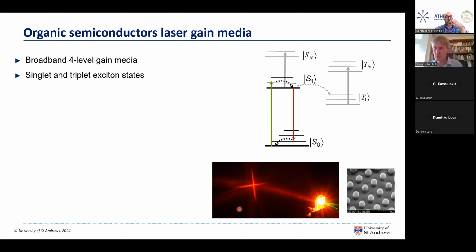So what about laser materials? Organic semiconductors are also quite interesting as laser gain media because their energy level systems are amenable to making a broadband 4-level gain medium, where we go between two electronic states in the molecule and a series of vibrational sub-levels within each electronic state. That allows us to make a 4-level laser gain medium, where we optically excite on one transition, and then the excitations relax to the lowest level of the first singlet exciton state, and then we can achieve stimulated emission on this red transition here.